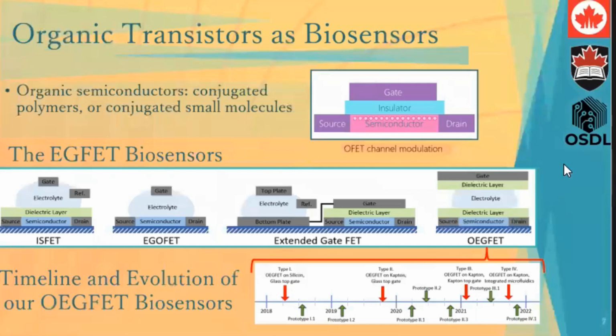The technology that we have been evolving for the last 3-4 years, we call it OEGFET. It's a little bit different from all three of them because the electrolyte is not directly in contact with either the gate or the semiconductor. We chose to do so because we wanted the ability to create a biofunctional layer, which can be tuned for specific bioassays. Most of the sensors that we have demonstrated in these configurations have been aptasensors. Aptamers are just as stable, perhaps more stable, than antibody-type biomolecules, so we like the idea of immobilizing them. They give us extended shelf life, and they can be patterned very easily on a variety of polymers using one-step functionalization. So that dielectric essentially is a biofunctional layer.